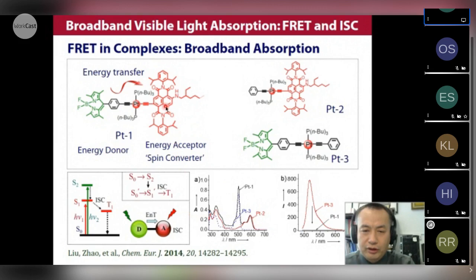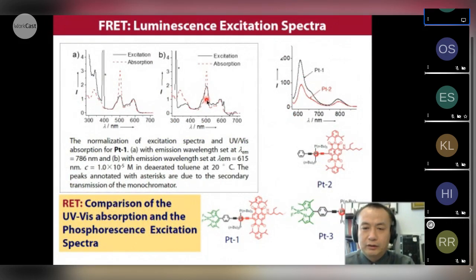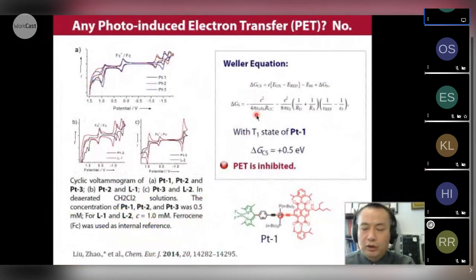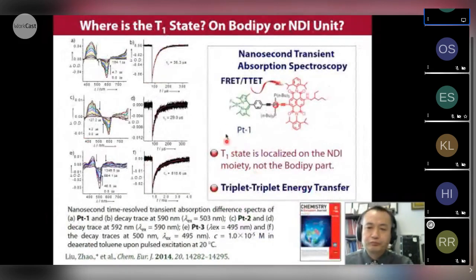And then because the acceptor is directly connected to the metal, we can expect efficient intersystem crossing for the energy acceptor. So we use some routine method to confirm we have FRET in this molecule. And then we also confirm we don't have electron transfer in this two-chromophore compound. In this case, we don't want to get a charge separated state. We want to have a high yield of triplet state. So we don't want photo-induced electron transfer. With the nanosecond transient absorption, we confirmed the triplet state is localized on NDI part, not on BODIPY part. This is dependent on the relative T1 energy levels of these two parts.